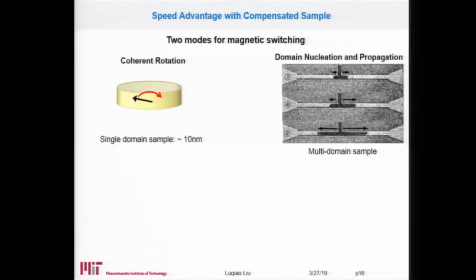Another possibility is, instead of looking at this kind of tiny device, we can look at a much larger device, which is micron size. And in those micron size devices, we know usually it's multi-domain. For multi-magnetic domains, we know the switching mechanism is usually due to domain nucleation and domain propagation. So the advantage of this type of measurement is that now you can make a much larger device. So the requirement on nanofabrication is much lower. And secondly, you can use nanosecond pulses instead of picosecond pulses to show the speed advantage. So this is the approach that we are going to utilize today to show the speed advantage.